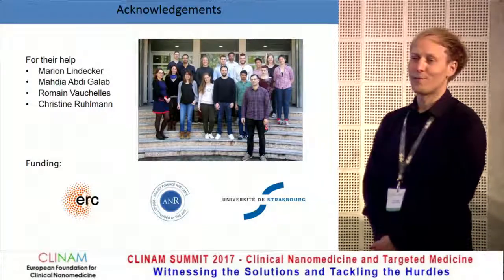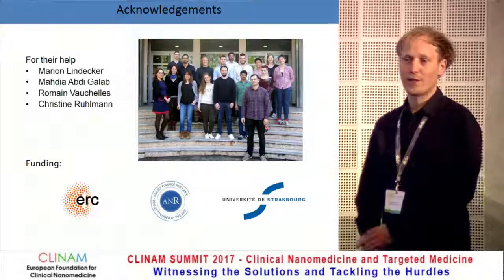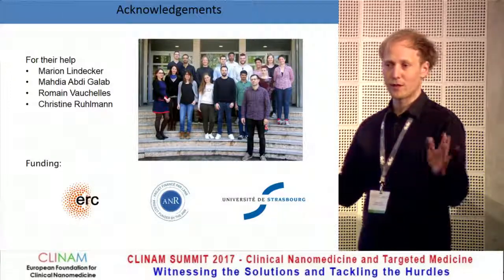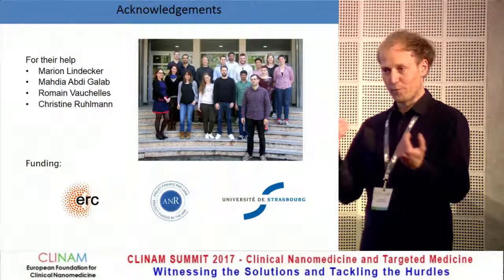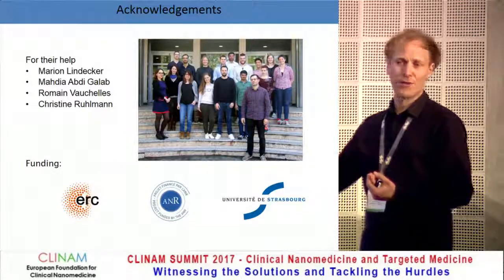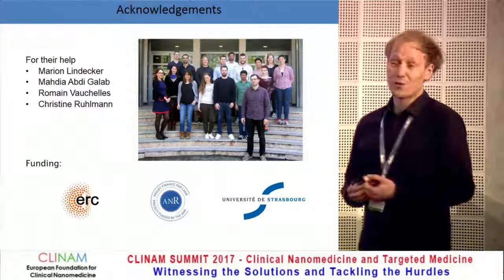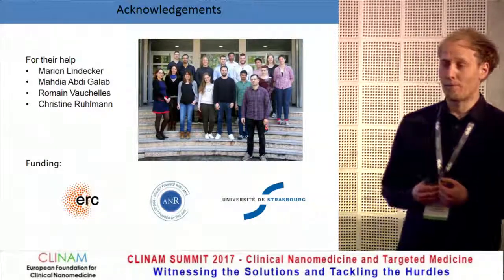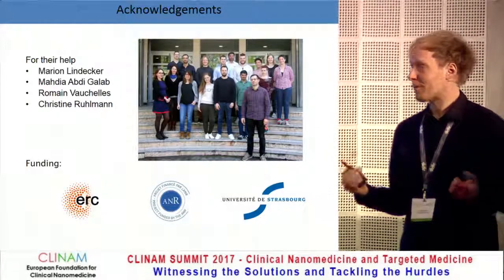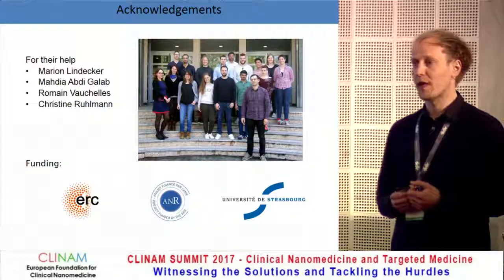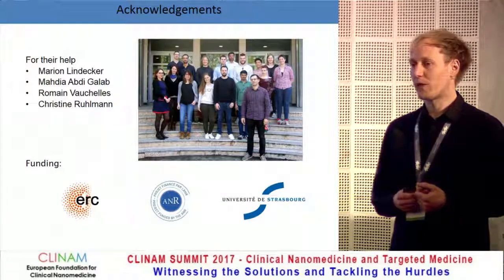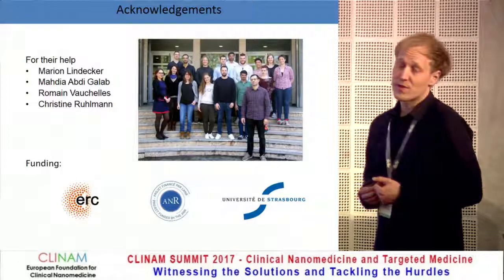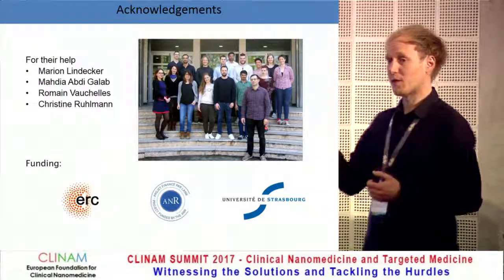That's simple mathematics. We start at about 10,000 nanoparticles per cell. From what we've seen, the nanoparticles are lost only through cell divisions — they're not degraded or excreted over the timescales we're looking at. If we go to something higher, like 50,000 nanoparticles, we should still have around 100 nanoparticles inside a cell to reliably distinguish a color code. The PLGA particles have degradation timeframes rather in the scale of tens of weeks to months, and they don't appear to be much excreted, at least in these cell lines.